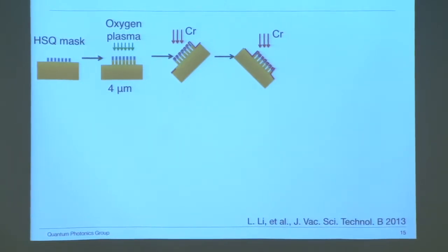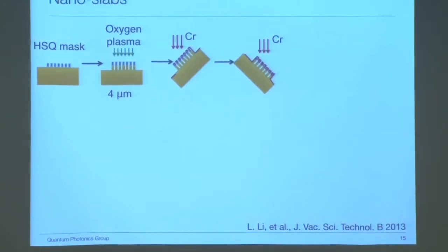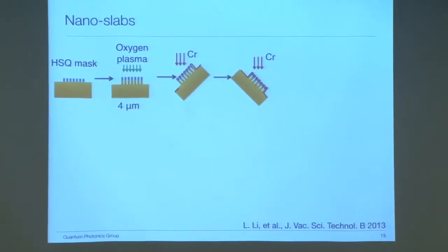To go deeper, we developed a way that is similar to silicon deep reactive ion etching, also known as the Bosch process. We deposit 50 nanometer chrome from both sides at a 45-degree angle. This chrome layer protects the sidewall and also adds a mask on top of the membrane. Because these membranes are closely spaced with each other, the chrome deposition will not go to the bottom of the diamond membrane. In this way, we can etch down further using oxygen plasma.